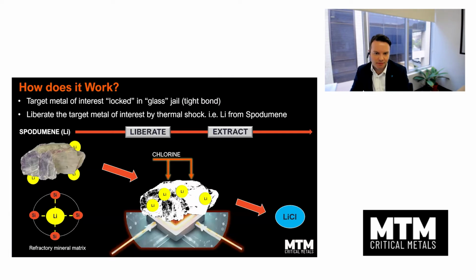Next slide, please. And then from a conceptual level, how does it work? Well, refractory really means that the target metal of interest is locked. And in this case, it's locked in a glass jail, or really a tight bond. So spodumene is an alumina silicate, and the lithium is bound strongly to the silica in a glass type formation. And that's why you really need a chemical sledgehammer to get it out. That's why you need to bake it at 1100 degrees for 3 hours.